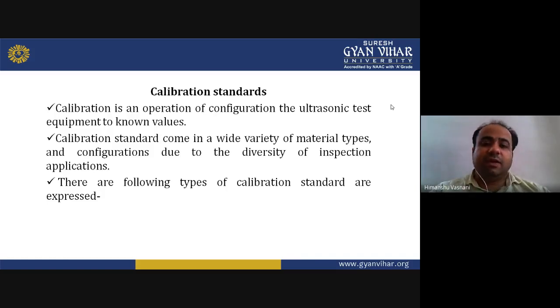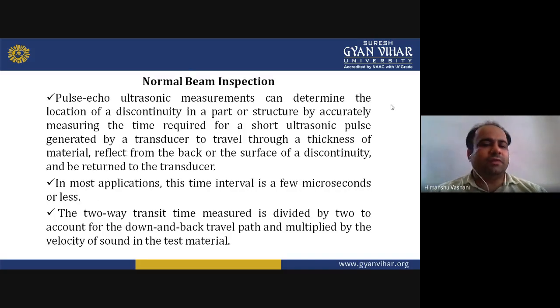Now there are the following types of calibration standard. The first one is normal beam inspection. In this, the pulse echo ultrasonic measurements can determine the location of a discontinuity in a part or structure by accurately measuring the time required for a short ultrasonic pulse generated by a transducer to travel through a thickness of material, reflect from the back or the surface of a discontinuity, and be returned to the transducer. This helps to find the discontinuity or defect in the part.